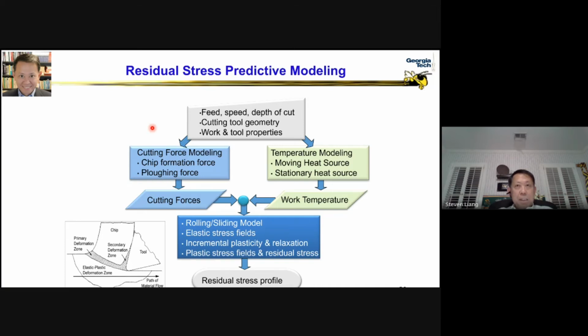But the copycat turbine blade will last 2-3 months, and it will break. The geometry of the turbine blade, the material of the turbine blade, Ti-6-4, are all exactly the same. The difference in the performance is in the residual stress, because the copycat duplicates my sponsor's geometry and materials, okay? But they cannot duplicate my sponsor's residual stress, because residual stress is intimately related to the process parameters and process conditions that you cannot duplicate as a competitor.